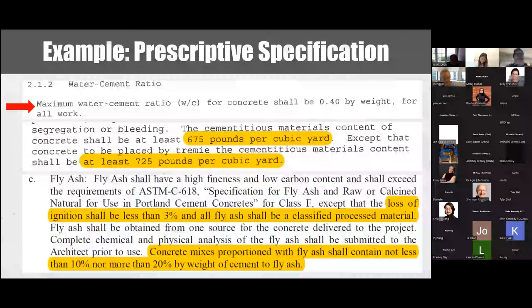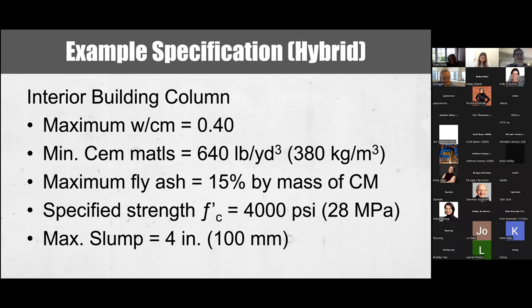Consider an example of a prescriptive specification for concrete used for interior building columns. The specification requires a 0.4 water to cement ratio, a minimum cement content of 640 pounds per cubic yard, a maximum fly ash content of 15% by mass of cementitious material, a compressive strength of 4,000 PSI, and a maximum slump of 4 inches. For this structural element, the critical performance characteristic is the compressive strength.